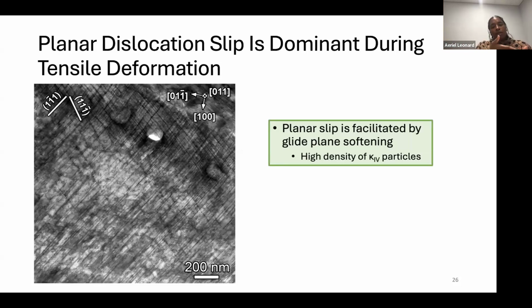It's important when you think about it from a hardening mechanism because it's an easy path, and as the dislocations approach the grain boundary, they start to pile up, right? What we saw before in some of the earlier things we talked about was that deformation was really constricted within these grains, and that we really weren't seeing a transfer of slip from grain to grain. Now, in some of the work that Nathan is doing in fatigue, we actually do see some slip transfer from grain to grain. But in this specific case, we weren't really seeing a lot of transfer from region to region in the tensile category. Regardless, we have a lot of planar slip because we have a lot of Kappa 4 particles, right? We have a lot of particles that are being sheared throughout our matrix. All of this is helping facilitate this glide plane softening or this planar slip that we're seeing in the material, which is interesting.